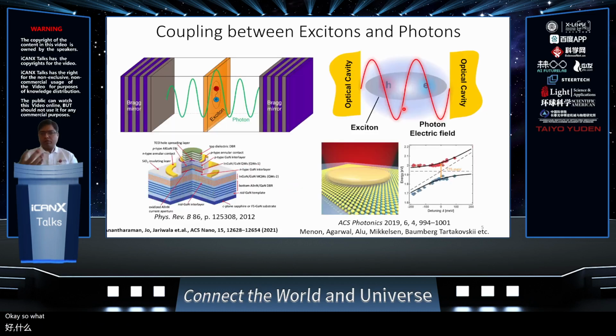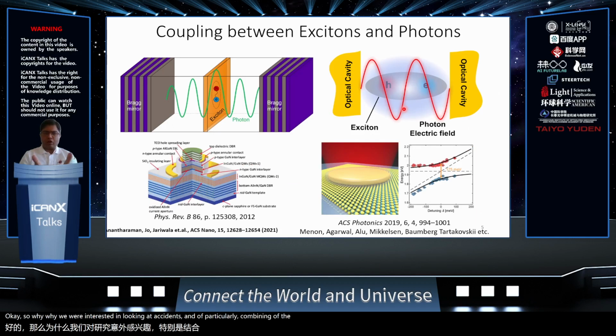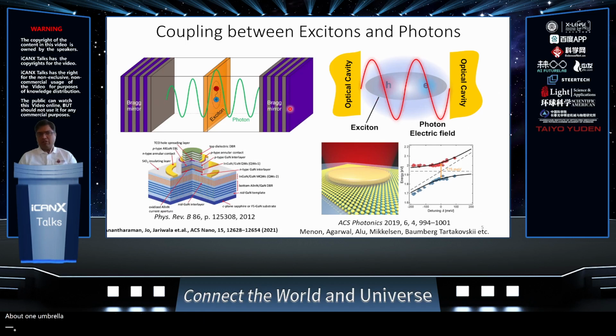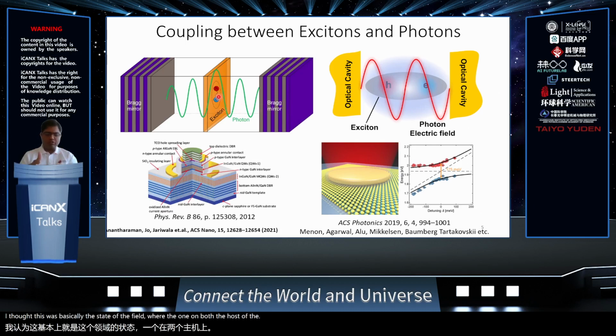Okay, so why we were interested in looking at excitons, and particularly combining excitons with photons trapped in cavity media, is because if you look about 30 years ago, all of the research in this field was dictated by epitaxially grown III-V materials, such as III-V quantum wells, which were sandwiched again in epitaxially grown Bragg mirrors, right? So this was basically the state of the field, where the quantum wells used to host excitons, and the photons trapped by Bragg mirrors would lead to strong light-matter coupling, leading to formation of exciton-polaritons.